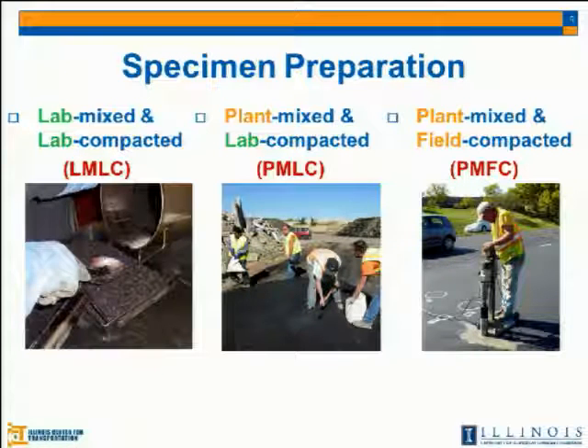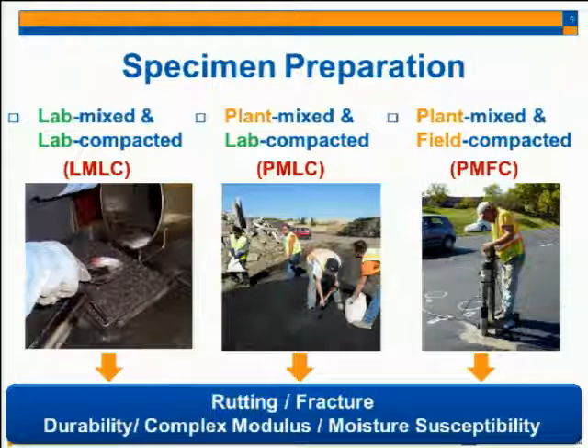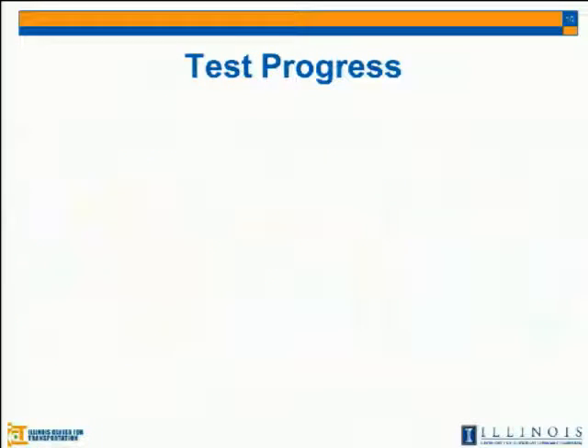Specimen preparation. We had three groups of specimens. The first one is we batch the aggregate and then mix in the lab and then compact in the lab using the gyratory compactor. Second one is we sample the loose material from the plant, and then compact in the lab. The third one is plant mixed and field compacted. This is the field mixed and then compacted by the roller in the field. We took all three samples and then did these 5 performance tests in the lab.